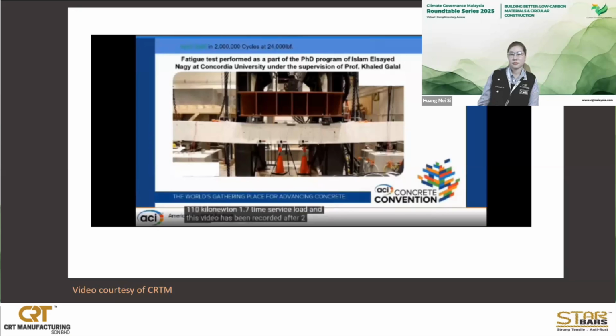We did the same test with steel, and it only lasted less than 20,000 cycles. See, 2 million cycles for GFRP versus 20,000 cycles. This material performs 100 times better than conventional steel.